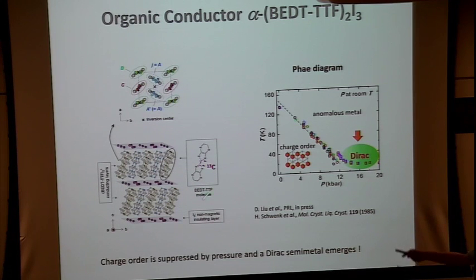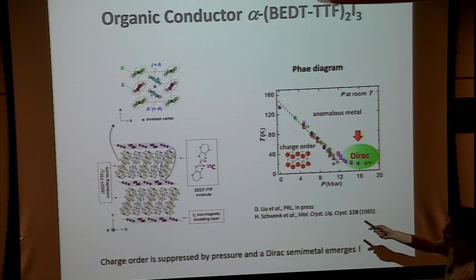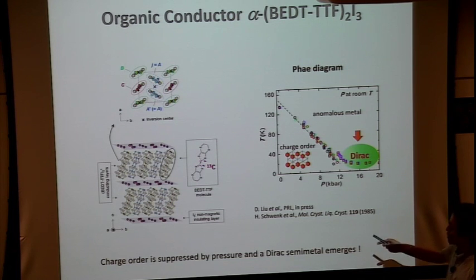Again, layered structures, seemingly similar to the copper type materials, but the difference is in the in-plane molecular arrangement. The copper type material has dimeric molecular arrangements. Dimers form two-dimensional layers, so a dimer carries one hole. So effectively half filling is realized. But in this case, no dimer. So this means the band filling is a quarter. And the unit cell contains 4 molecules: A, A', B, C. The two A molecules are equivalent, but B and C are non-equivalent.